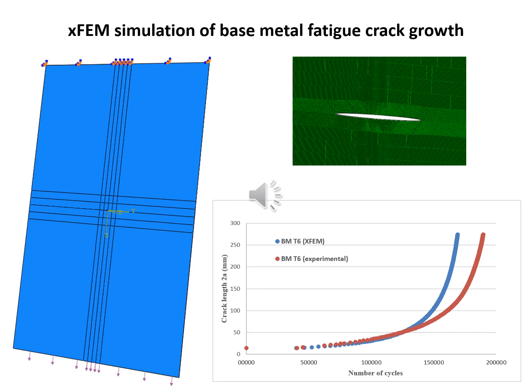We have almost perfect matching, and then once nonlinearity comes to the life, we can see that crack grows faster in numerical simulation than in experimental research. And that is something that we liked, because although agreement was not perfect, but at least it was a conservative simulation, which enables us to trust our numerical results, at least from point of view of structural integrity.